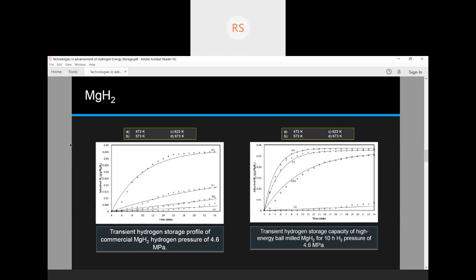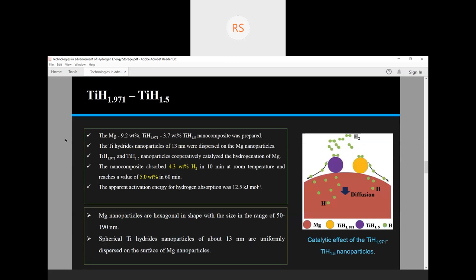They generally make the material more porous, which enhances the hydrogen storage capacity. The crystallite size decreases to the nanoscale, and the adsorption kinetics as well as the capacity of milled MgH2 are enhanced. But the main problem that still arises is that the operating temperature conditions are very high and not practically applicable to fuel cells. So to enhance the working of MgH2, there are certain catalysts that we have used in the doping. The first one I would like to mention is titanium hydride catalyst. In order to improve the sorption kinetics of Mg at room temperature, the nanocomposite was prepared by plasma metal reaction, and hydrogenation and dehydrogenation were carried out at 673 Kelvin.